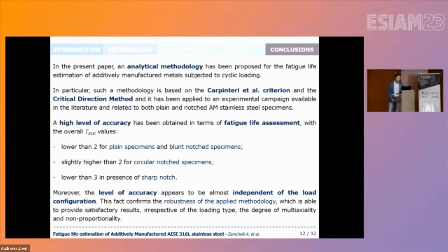So in the present paper, an analytical methodology has been proposed for the fatigue life estimation of additively manufactured metals subjected to cyclic loading. And in particular, this methodology is based on the joint application of the Carpinteri criterion and the critical direction method, and it has been applied to an experimental campaign which was taken from the literature. And it was related to both plain and notched AM stainless steel specimens.